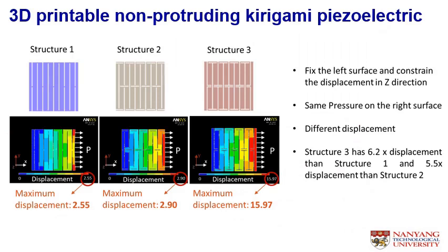From the simulation, we can see that structure 2 and structure 3, which has horizontal cuts at the end, is giving a different displacement compared to the one in structure 1 without the horizontal cuts. Structure 3 has about 6 times better displacement compared to structure 1 and 5 times better compared to structure 2.